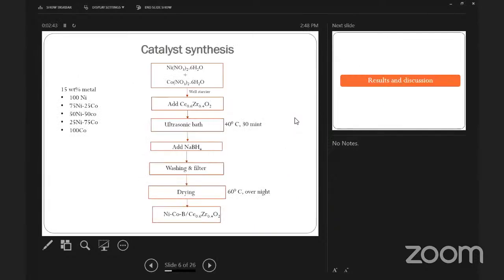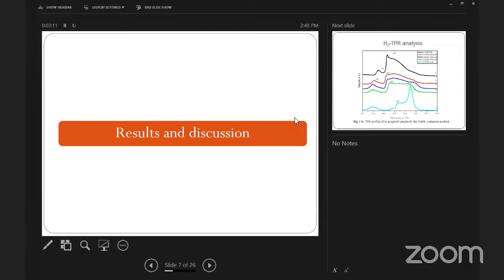This is the catalyst preparation part, in which I have used nickel nitrate and cobalt nitrate and added ceria zirconia mixed oxide, and used the NaBH4 reduction method. I added NaBH4 on the basis of 3% of boron, then washed it, filtered it, and dried it in a vacuum oven, and then it is ready to use for the dry reforming reaction.